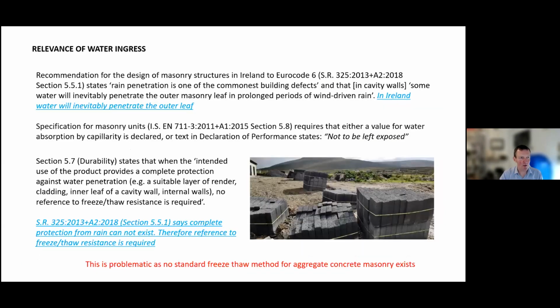Now, the relevance of water ingress really comes down to, in my opinion, this standard, the Eurocode 6 SR325. What it says in one section is that rain penetration is one of the commonest building defects, and that in cavity walls, some water will inevitably penetrate the outer masonry leaf in prolonged periods of wind-driven rain. So what it's saying to me is that in Ireland, rain will inevitably penetrate the outer leaf. This is of core importance because the specification for masonry units, if they're exposed, is that the manufacturer will declare the absorption by capillarity, the coefficient of water absorption, or they will put on not to be left exposed.